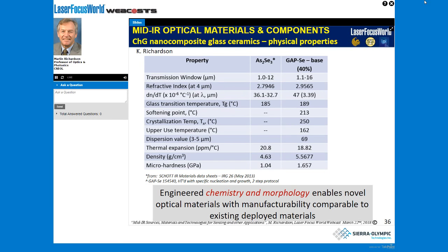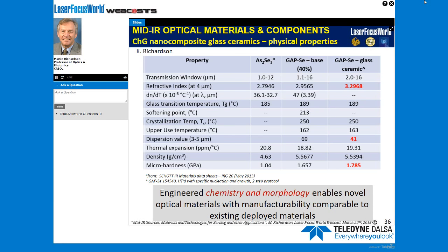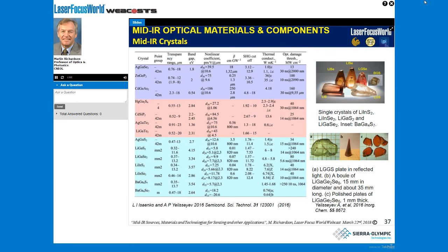So, perhaps in summary, here are many of the physical characteristics of these nanocomposite glass ceramics compared with conventional arsenic selenide, the GAP-Se base material, and now with these glass ceramic materials, you can see how we can get increased refractive index. Most other parameters will remain constant, but the dispersion can be decreased, and the micro hardness can be increased. So an advantage for chalcogenide materials.